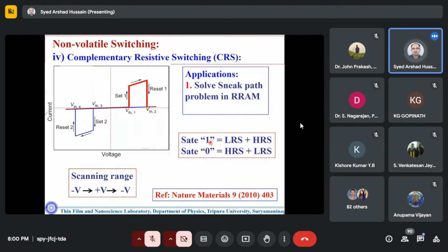Say state 1 is low resistance state plus high resistance state. So maybe low resistance state here, then at the same bias, you see high resistance state here. So 1 is low resistance plus high resistance. It's a combination of two states. Similarly, 0 is the opposite, so it's high resistance state plus low resistance state. So in any state, either 0 or 1, there will not be any conduction between two electrodes or across the device. So it also has some advantage. We will see with some examples later.